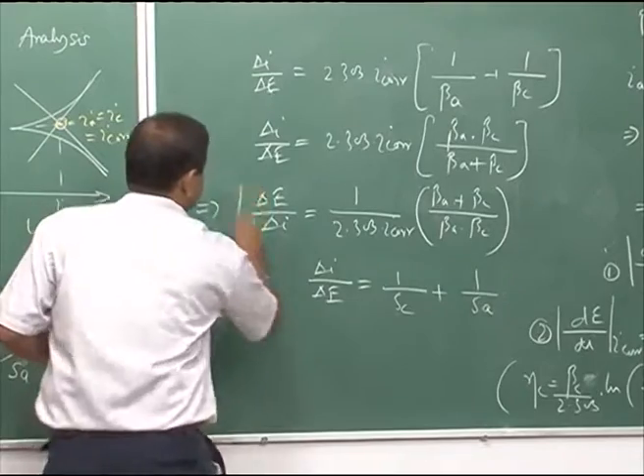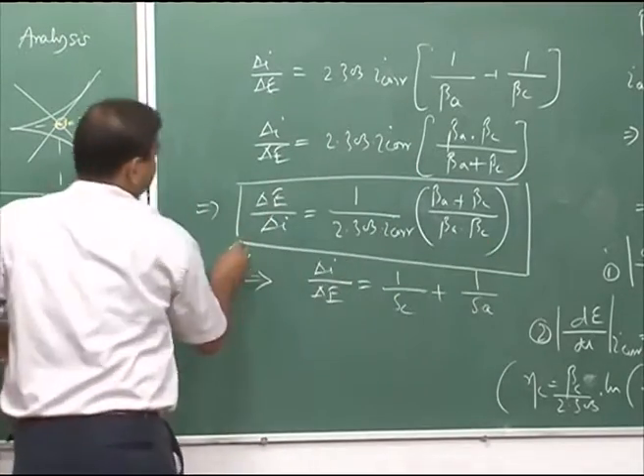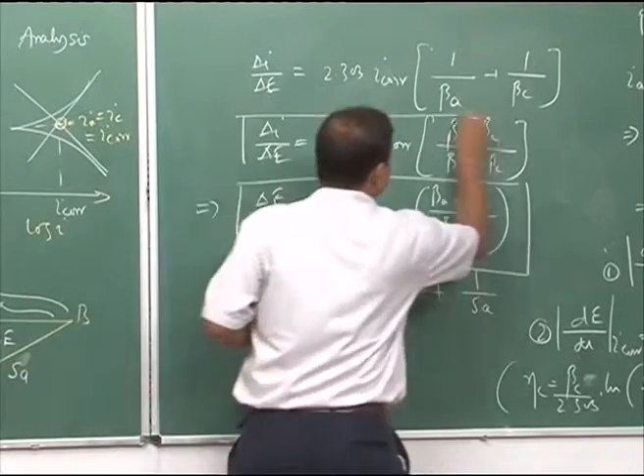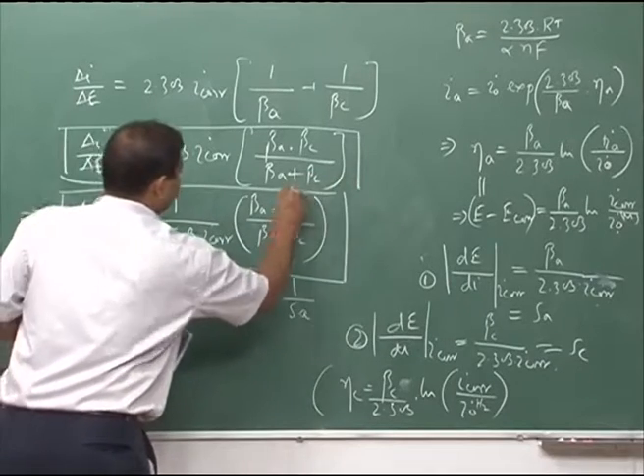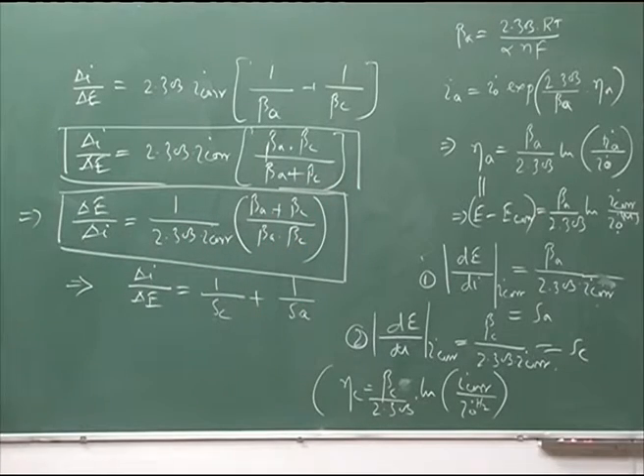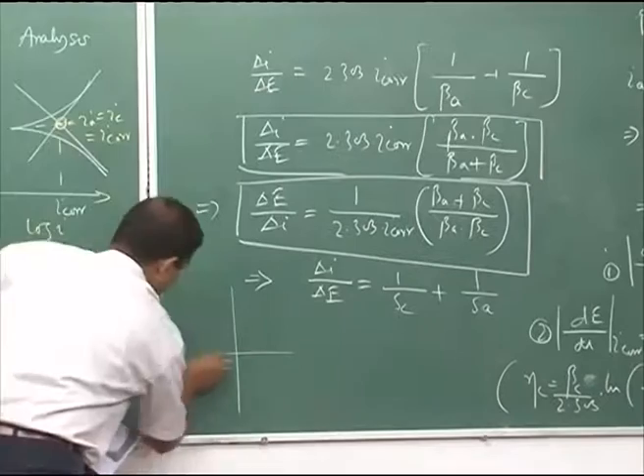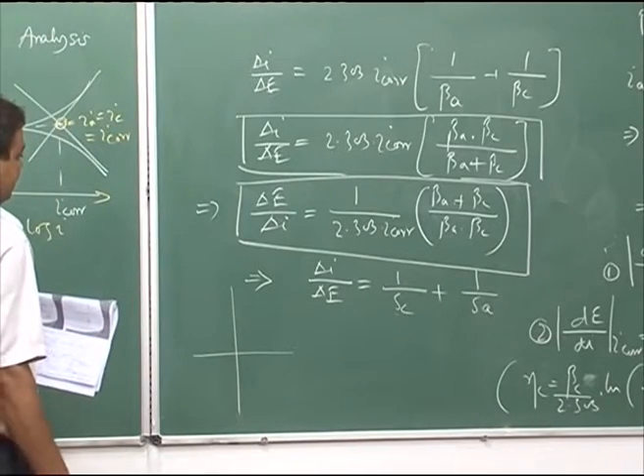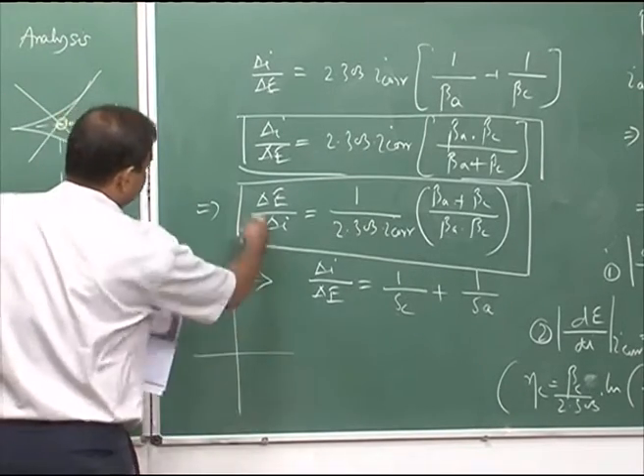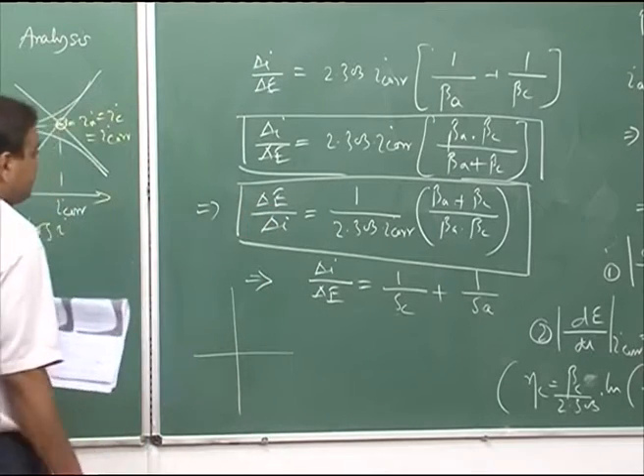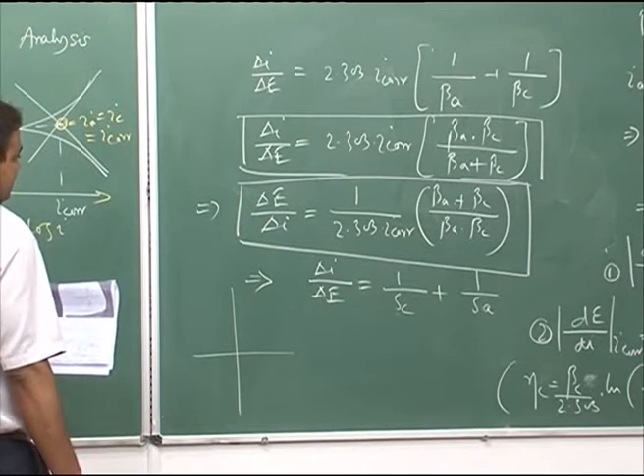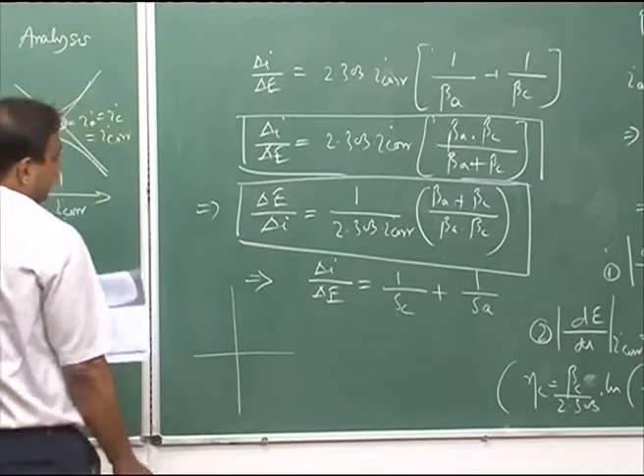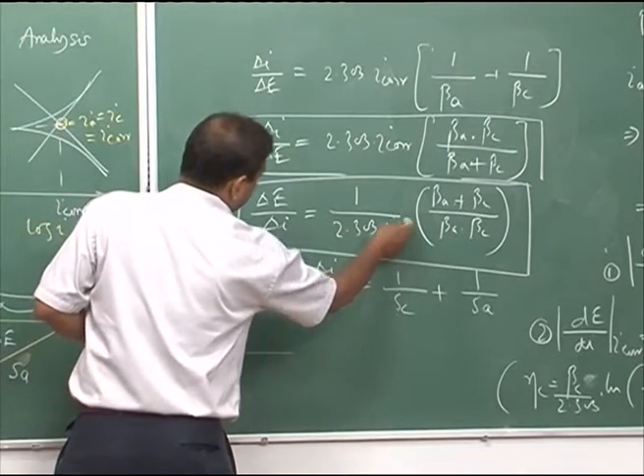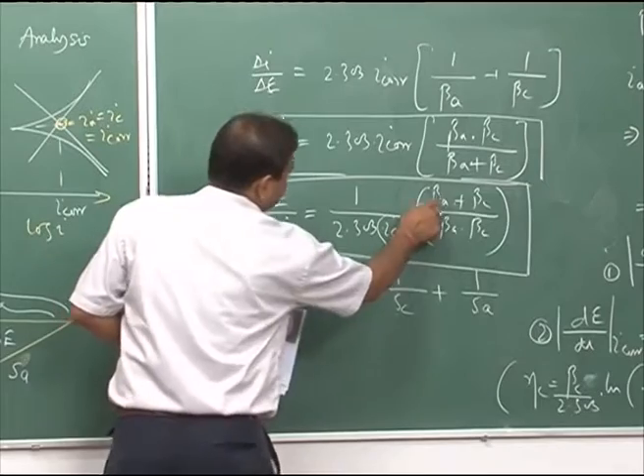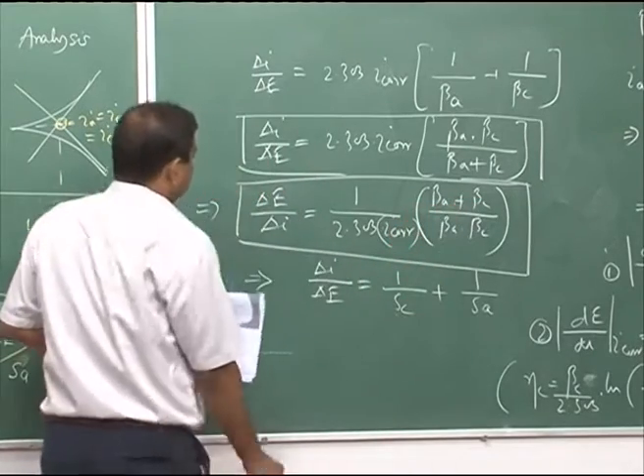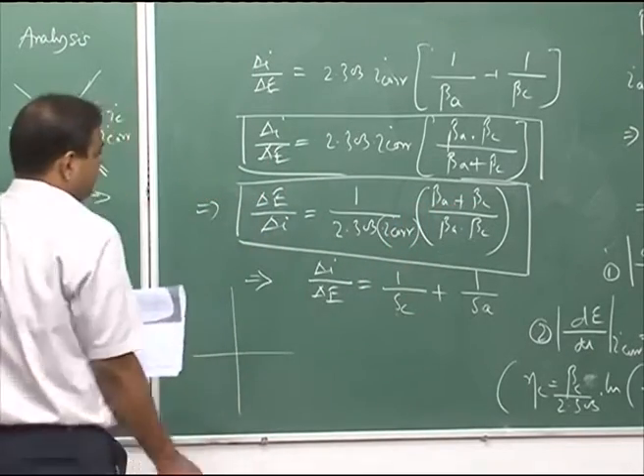So, this is the expression, or we can use this expression, any of this expression. We see that whenever we have a small over voltage, then the slope of that over voltage versus current plot can give you the I corr value, because this one we know, and if we know this, then we can get this.